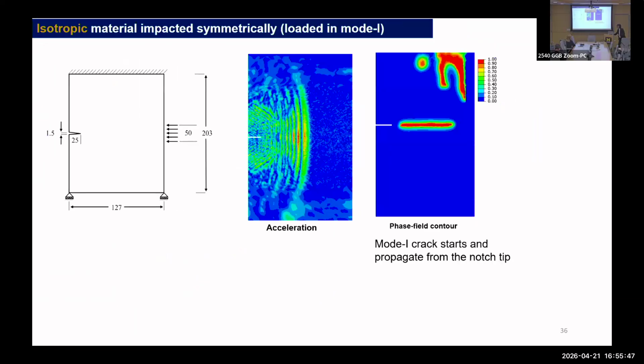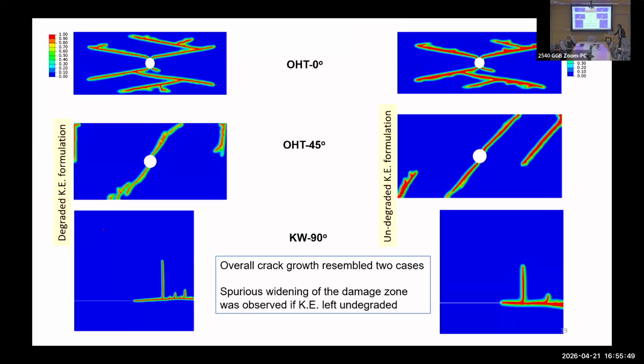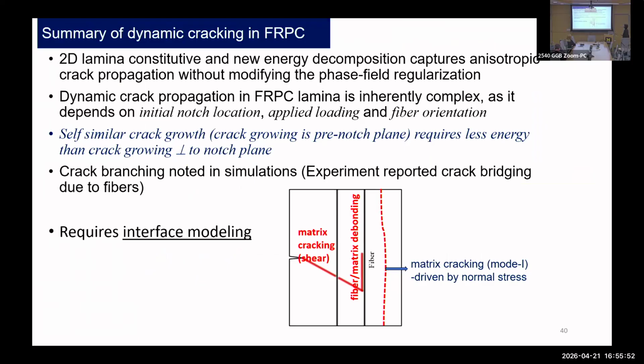So I will probably jump to the conclusions because I don't think we have enough time. So the second part summary is basically that we have used this 2D lamina level constitutive description combined with a new energy decomposition based on the local stress description to capture the anisotropic crack propagation. In this case, we do not need to incorporate that anisotropy in the phase field regularization. So we can get rid of that anisotropic tensor and the scalar variable associated with it. We see that the dynamic crack propagation, which is inherently complex, can be captured really well.